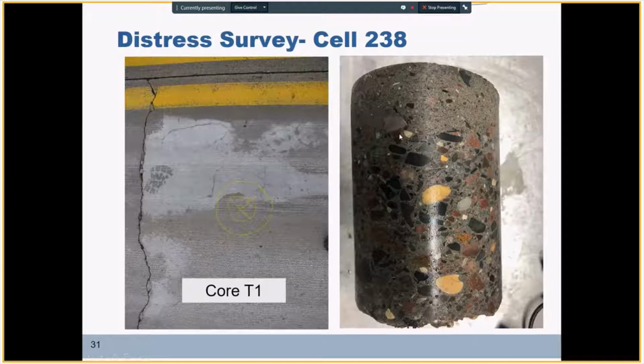Because we had this mortar at the surface with no coarse aggregates to restrain shrinkage and provide stiffness for the hardened concrete, we had that cracking. With the adjacent joint and the wide open crack, we could expect more water penetration into the hardened concrete and progressive cracking in the future, add to this the load by the ATG truck. The combination of these observations, I would say, were the reason for this type of crack.